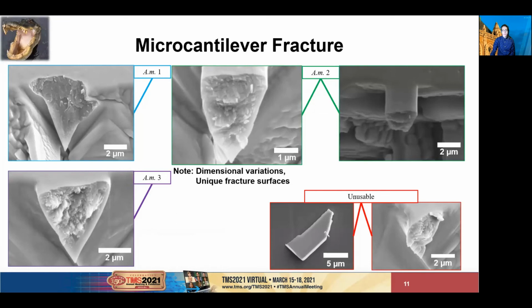The fracture surfaces of these microcantilevers show some interesting behavior. On AM1, the crack propagated along the long side of the nanocrystals, as indicated by the relatively smooth surface. Below that, we see a rough surface that looks somewhat like fiber pullout in composites. And indeed, enamel is a biocomposite. It is not clear in AM3 if the crack solely went around the nanocrystals or if it transversely fractured through some of them. This last example here shows sort of a stair-step serrated pattern, a combination of the other two, likely following the growth lines separating the hydroxyapatite crystals.